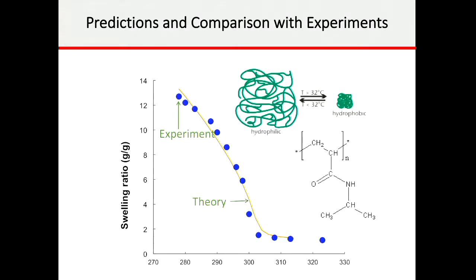The experience, of course, is amazing when the theory fits the experiments. And as you can see, we had N-isopropyl acrylamide as a molecule, and this is very interesting because the amide group is hydrophilic, and the isopropyl is hydrophobic. So in the same molecule, you have both hydrophilicity and hydrophobicity. The amide can interact with other amides hydrophilically. The isopropyl will have hydrophobic interactions with other groups. And interestingly, you can see the theory and experiment matched very well indeed.